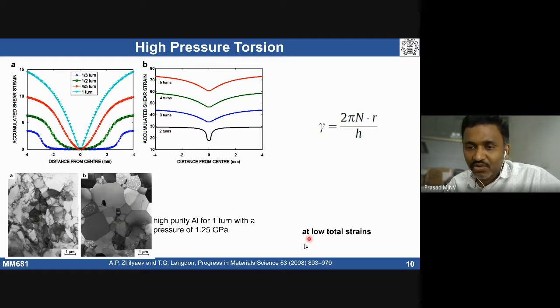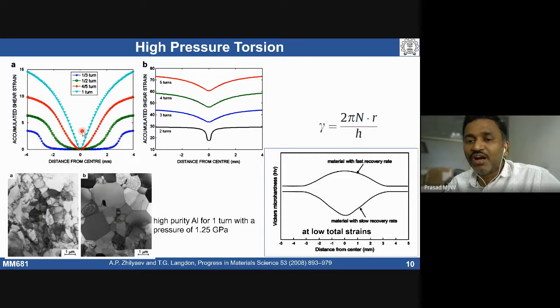At low strains, typically, if we take two different types of materials, low stacking fault energy material and high stacking fault energy material, at low strains, meaning initially below 1 turn, hardness is going to vary like this. If we take a disc specimen, materials with a fast recovery rate, which is basically aluminum, high stacking fault energy materials, will have relatively higher hardness at the center as compared to the edge. Materials which undergo slow recovery, typically we do see this kind of change in hardness. Because when there is a recovery, that means your strength is going to come down.